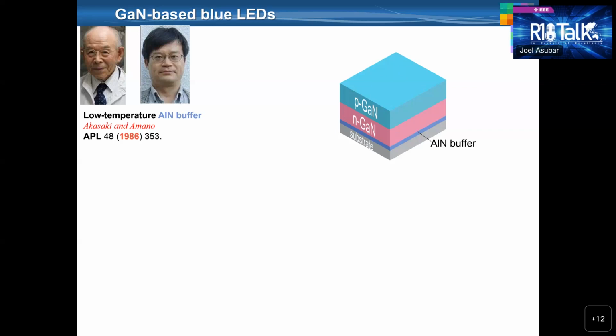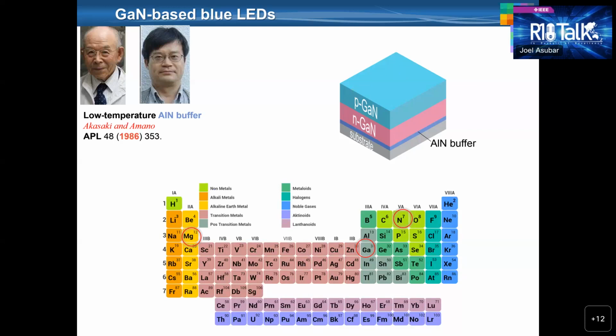In order to fabricate practical LEDs, P-type and N-type gallium nitride materials are needed for the PN junctions. While N-type gallium nitride is relatively easier to obtain, the problem was to obtain the P-type conductivity. In order to obtain P-type conductivity, gallium nitride is doped with magnesium. Since magnesium is a group 2 element, it has 2 valence electrons, 1 less compared to the 3 valence electrons of group 3 gallium. So if a magnesium atom occupies a gallium site in a gallium nitride crystal, a deficiency of electrons, or hole, will be generated.